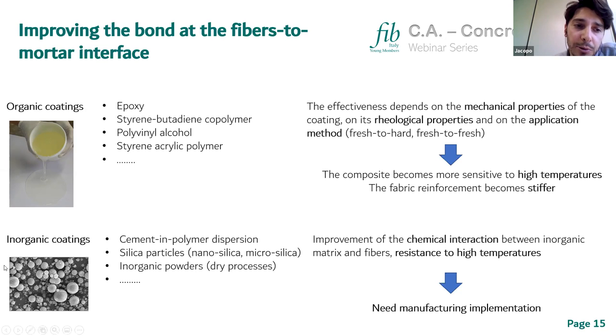In the last years, inorganic coatings have also been developed, such as cement in polymer dispersion, silica particles, inorganic powders. In this case, we have an improvement of the chemical interaction between the inorganic matrix and the fibers. We also have a higher resistance to high temperatures, even if there are still not many studies on this topic. Of course, the manufacturing process is more difficult, and so we need further implementation.